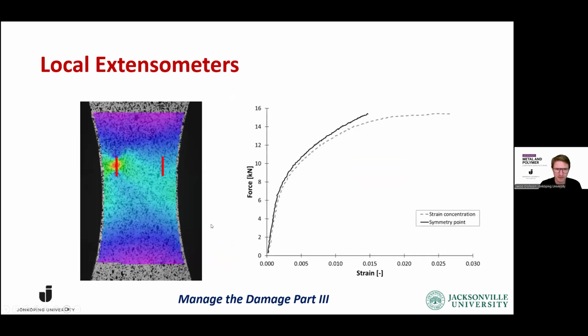One good thing with using this digital image correlation technique is that we can also go in and place local extensometers after the test on different positions. So if we measure the straining behavior of the strain concentration and at a symmetry point, which is located on the same level, but on the other side of the center line, we can see on the force strain curve that we plot that the hidden damage here, the oxide, has really caused a different straining behavior than the rest of the material. It's much higher strain here, which also leads to the premature fracture here.